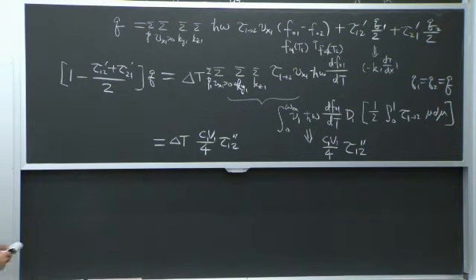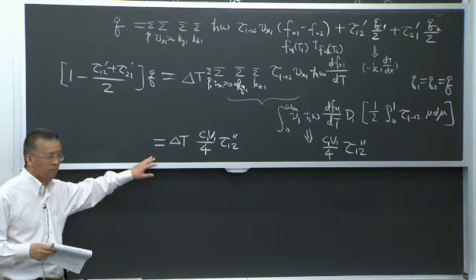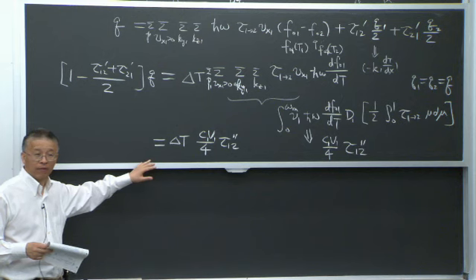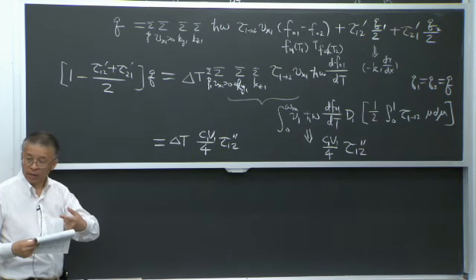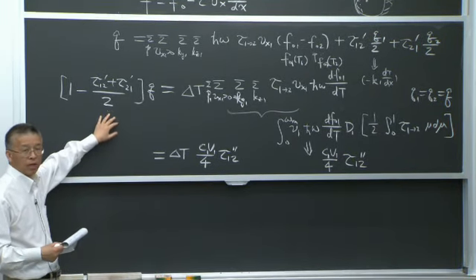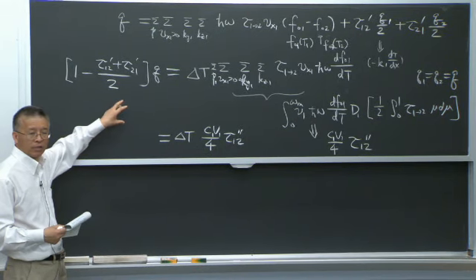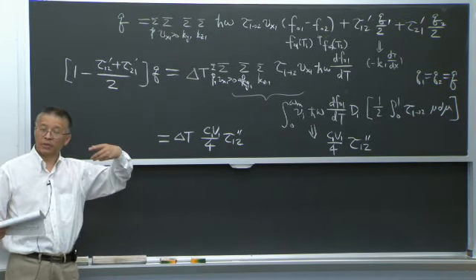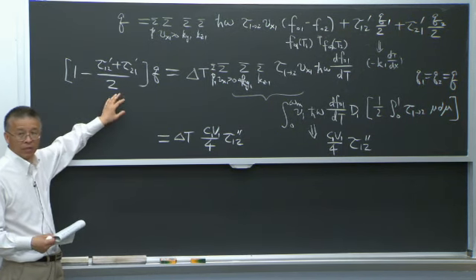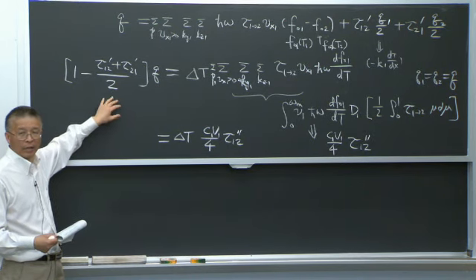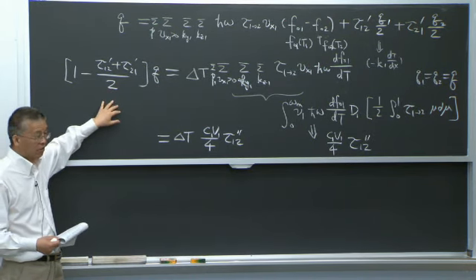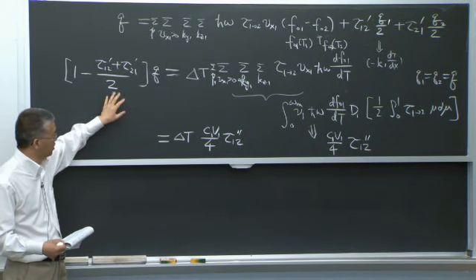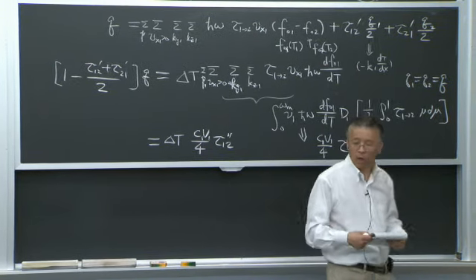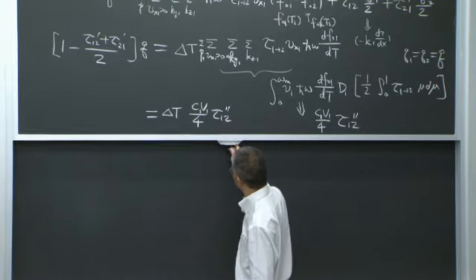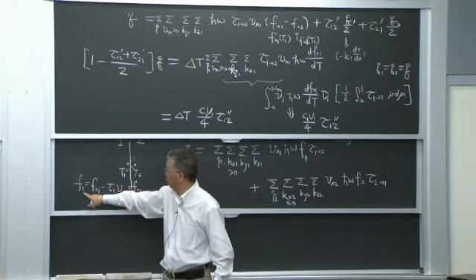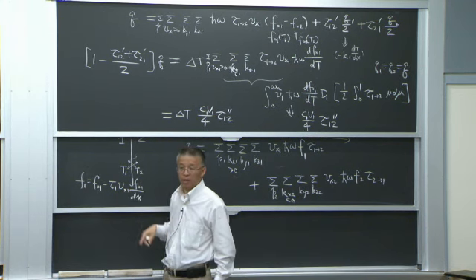So this is slightly different from what you had in chapter 5. In chapter 5, we did the interface thermal boundary resistance, and what they didn't have is this two term, right? But later on, when I discussed the difference between emitted temperature and equilibrium temperature, go back and look at the derivation. In that case, you add these two terms. So there's a similarity, except there is a little difference in the angle weighting itself, because there we did not consider this diffusion flux distribution. We did not consider that F has this tau V deviation, say flux.